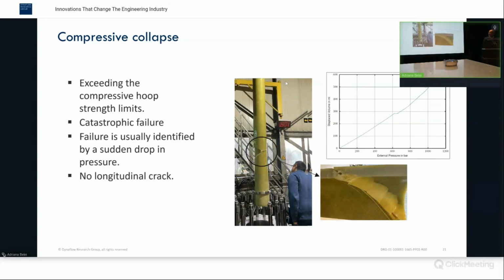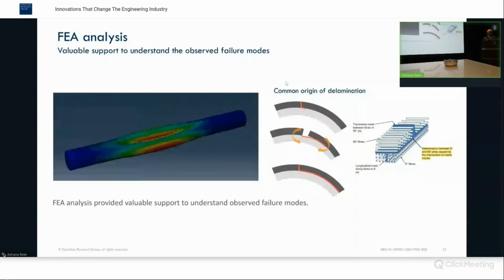The compressive collapse failure is a catastrophic failure, characterized by a sudden drop in collapse pressure, as you can see on the plot at the right side, and it will cause more severe catastrophic damage to your pipe. To understand the failure mechanisms we observed during the tests, a substantial finite element analysis was carried out by Dynaflow, where we looked at the morphology of the cracks and tried to understand, with the support of finite element analysis, what actually happened.